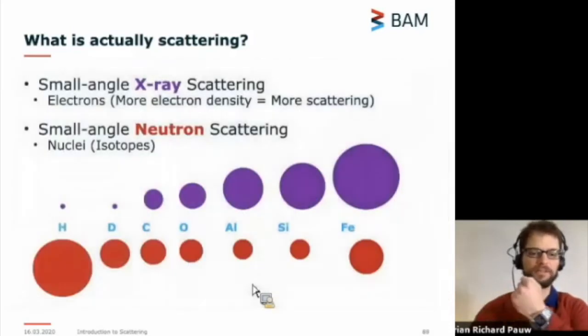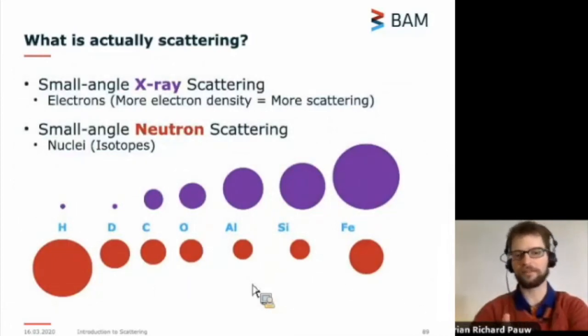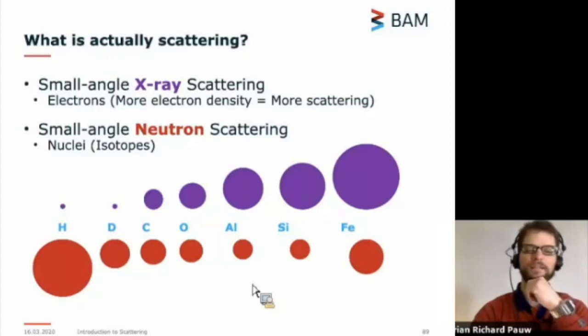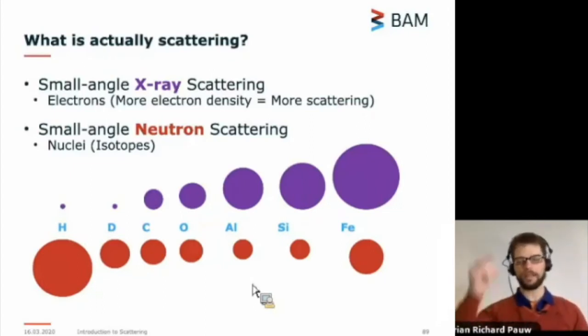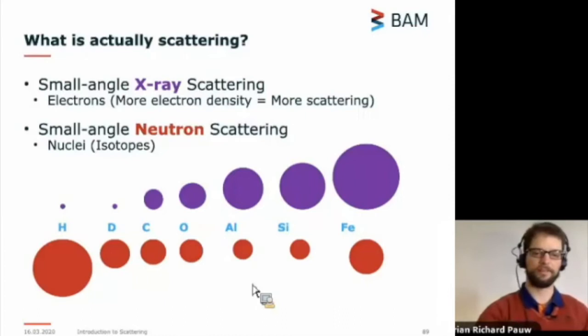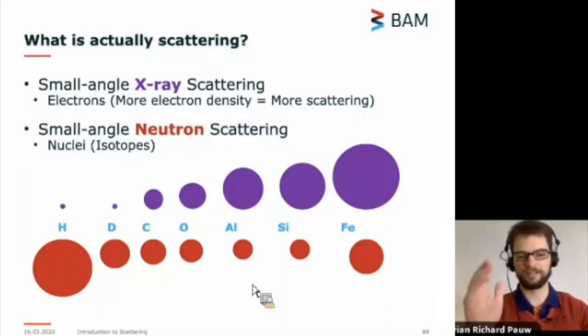All right, I mentioned a little bit about neutron scattering. So here is a visualization of the differences that we have between X-rays and neutrons. You see the contrasts are vastly different. And you can exploit this difference in contrast to highlight parts of your structure. I have an example about that later. But that's the main difference, the main message to pick up between X-ray and neutron scattering: the big difference in contrast between the elements.